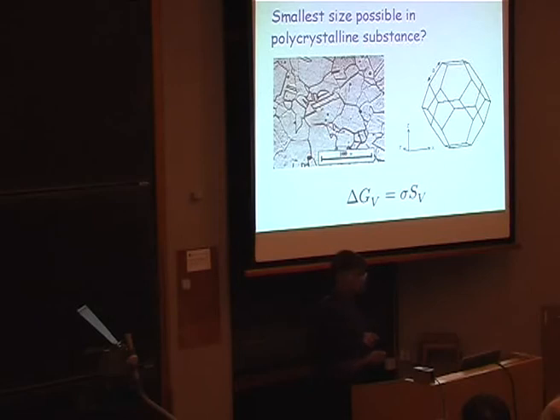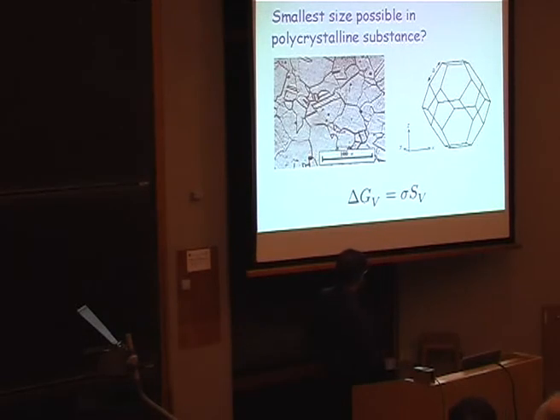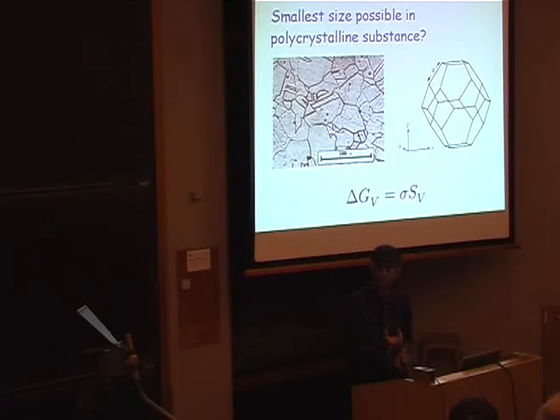And the big improvements in properties happened because the crystal size was reduced by microalloy. So you introduce certain precipitates which stop the grains from growing. So I'd like to find out what is the smallest grain size that I could get by using thermomechanical processing, which is used to produce these steels. Well, the grains are of this shape. I can work out how much surface we have per unit volume, and multiply it by the surface energy, and that's the amount of free energy that's consumed in forming the grain boundaries. So if I use up all the free energy from phase transformation to create grain boundaries, that should give me the limiting grain size.